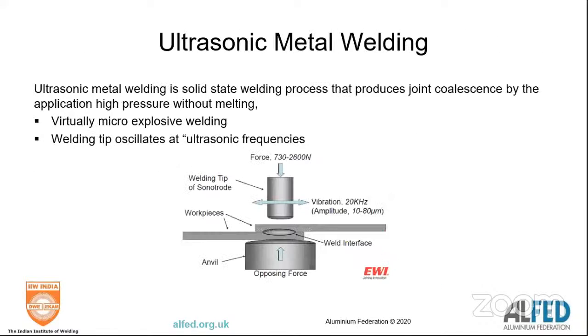So I'm going to pick up on the first one. There's a lot of work going on in the automotive industry in the UK and particularly in the USA, and Ford are now starting to ultrasonically weld aluminium. In essence, ultrasonic welding is a micro explosive weld. What happens is the welding tip is vibrating at ultrasonic frequencies.